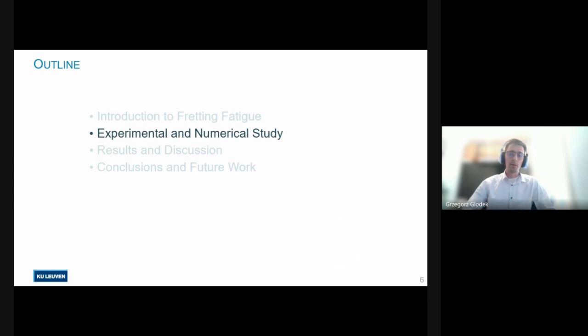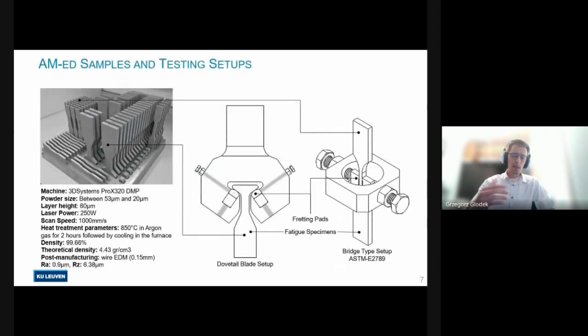Now, fretting fatigue can be a challenging phenomenon to study, and it often requires an experimental and numerical approach. In the next few slides, I'll go over the methodology I used in my research, starting with the selective laser melting process itself. So the material in question, TI-64, the parts were manufactured using a 3D Systems ProX 320 metal printer. The density of the final components is equal to 99.6% of the theoretical density of around 4.4 grams per cubic centimeter.